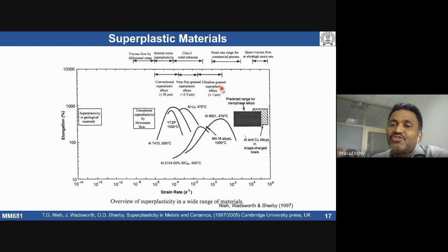Typically 10 power minus 2 per second and above is considered high strain rate superplasticity. That means we need to have a fine grain size. At the same time, this grain size has to be thermally stable. Otherwise, we know it is going to grow like anything; a fine grain size can grow at a more rapid rate than a coarse grain size. So one has to have a stable grain size, and it has to be much finer. Then only can I get high strain rate superplasticity.